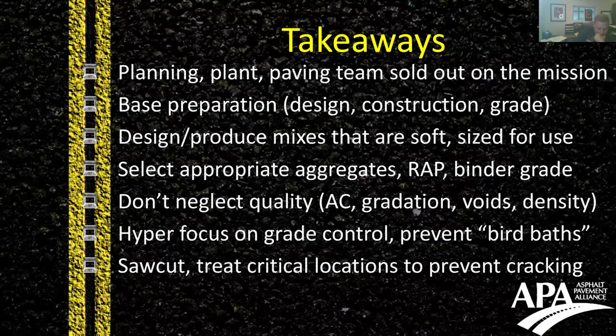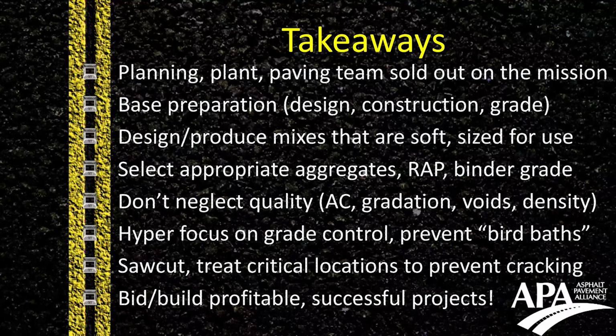With cracking, you can saw and seal the cracking in order to control it, and that's not something that we talked about in the presentation. But there are some really good standard practices that you can find online. Essentially, with saw and seal, what you're saying is, I'm probably going to have a crack here over the long term, so I'm going to do a masonry saw cut, and I'm going to fill it up with a crack sealer before I do my final coating. That way I'm going to manage the crack and make sure that it doesn't materialize on the surface in an uncontrolled, ugly, irregular way.